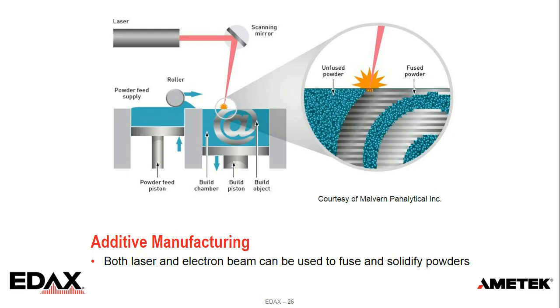This is an example from Malvern Panalytical, where you have a bed of powdered material. We hit the powder, in this case with a laser, but both lasers and electron beams can be used. It fuses the powder particles together and solidifies them, so we can use the laser to raster out the area we're interested in. Once the layer is complete, we drop the build platform down, reset the powder on top, and do another layer. And so we can build complex shapes generally pretty easily with additive manufacturing.